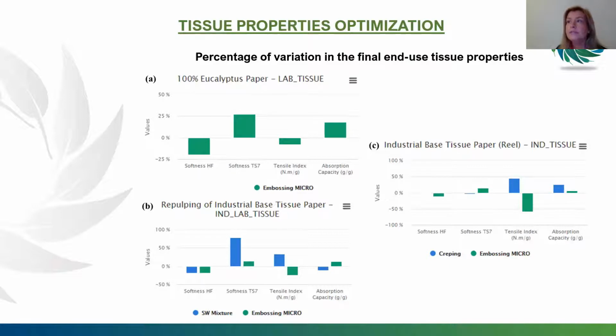The embossing has a negative influence on the tensile index that comes because of the fiber and structure deformations induced by the applied pressure of this operation. The modification of the structures in the Z direction increases the TS7 parameter and consequently decreases the hand feel softness parameter. Globally, the embossing operation has a negative impact on mechanical properties and softness, and on the other hand, increases the thickness in the Z direction and consequently increases the bulk.